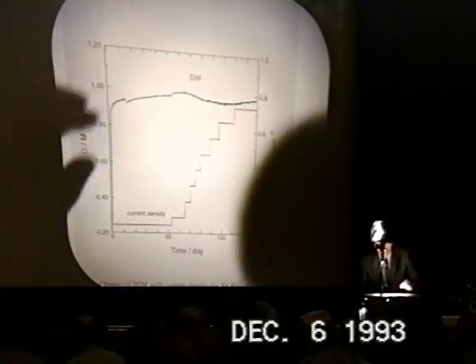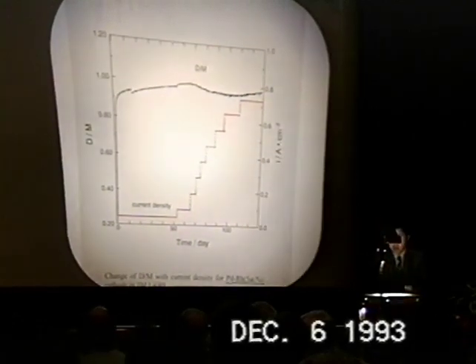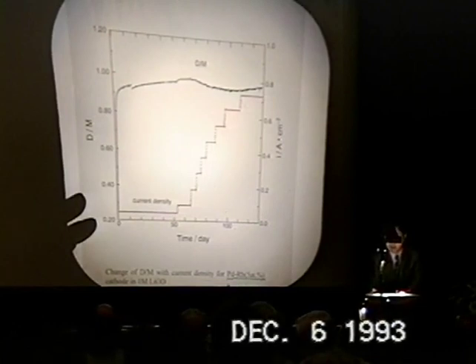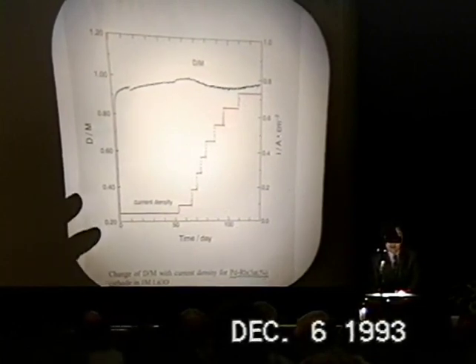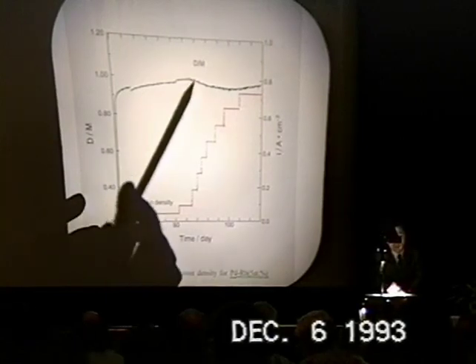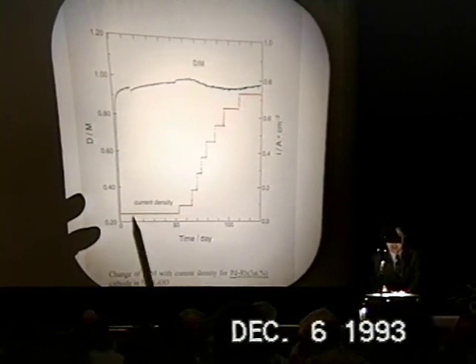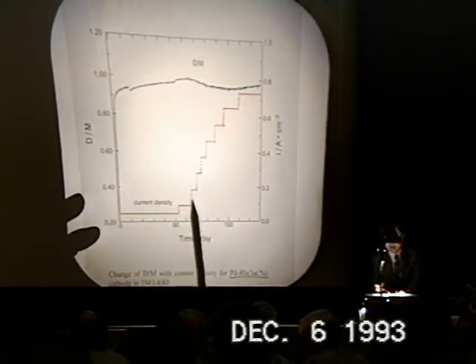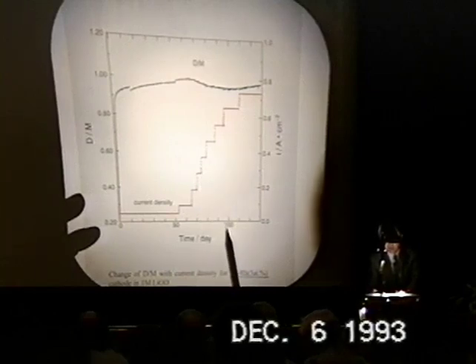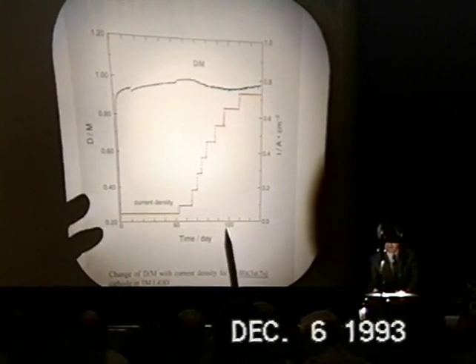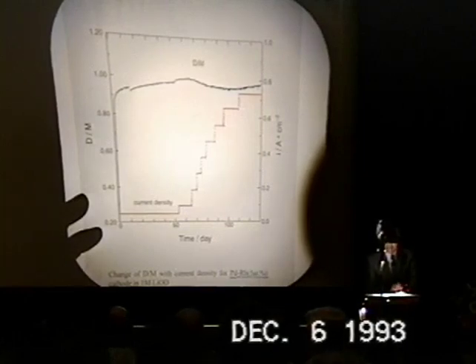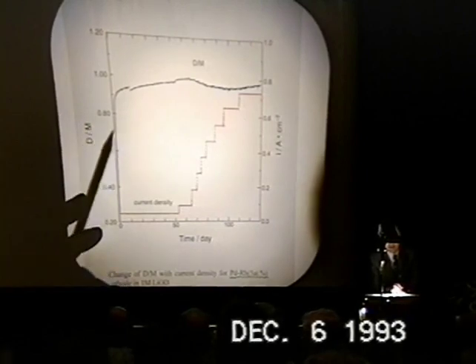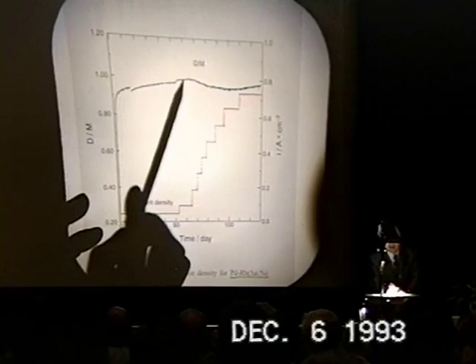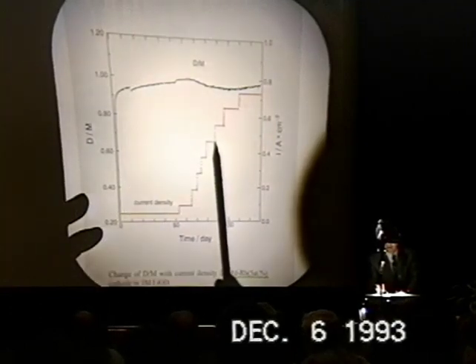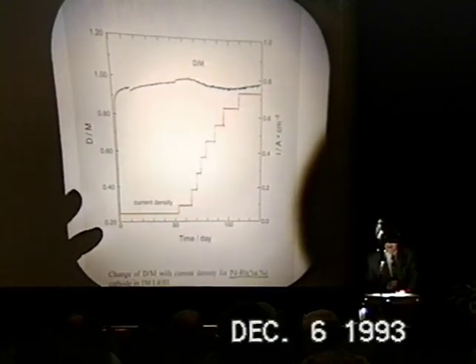So the loading of palladium rhodium alloys, for 5% rhodium palladium alloys in 1 molar LiOD. I'm showing here the change of D over M as a function of time, when we change the current density in a stepwise manner, shown in this way. So the experiments lasted for nearly 120 days, which is still continuing actually. But what I would like to point out is the D over M is very close to 1 in this range. After some current density, D over M comes down.